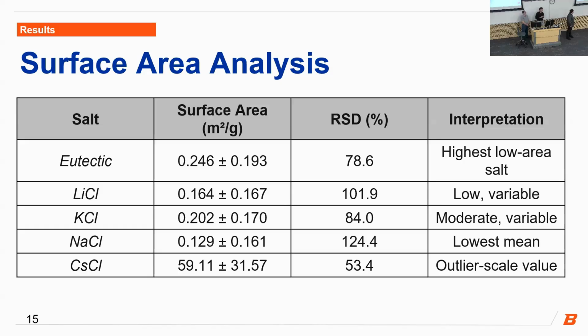The high RSD means that the measurements are very noisy, and some of the small differences in the results can be reflected in the powder packing, sample heterogeneity, and low area BET measurement sensitivity. Another important observation is that our cesium chloride values have a completely different magnitude and should be approached with caution. However, it's important to note that nothing in the testing procedure changed between any of the salts.